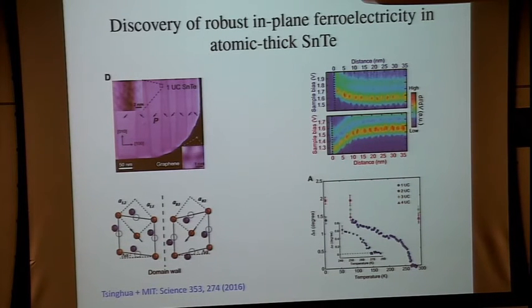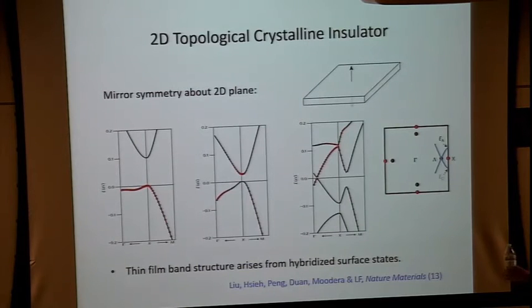So this is a rare example of robust in-plane ferroelectricity in atomically thin materials. Usually if you take a bulk material and make it very, very thin, the ferroelectric transition temperature goes down. But here it goes up. We don't completely understand why, but we think that it may have to do with this particular band structure that comes from the hybridized surface states.